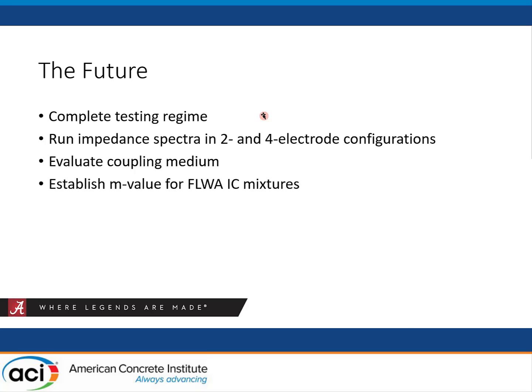We're also going to very extensively evaluate this coupling medium. My electrical engineering colleague actually developed a printed circuit board that can switch and represent different residual impedances, and that was part of that paper I showed earlier in the presentation. So we're going to look at that, and finally we're going to establish some recommendation for an M value that we can use to correlate between sealed and saturated lightweight internally cured mixtures in terms of their resistivity values.